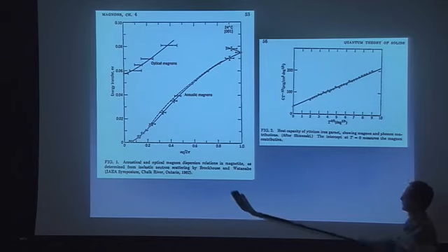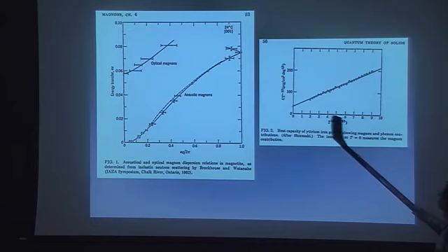And once again, this is neutron scattering by Brockhouse. So this is made in Canada, proudly. Another thing that I'm showing here is the heat capacity. In this case, this is yttrium iron garnet, which is another ferromagnet. And the nice thing about this is that it's an insulator. So there's no contribution from electrons to specific heat. So the only contribution is specific heat of